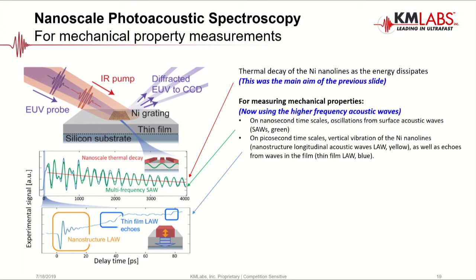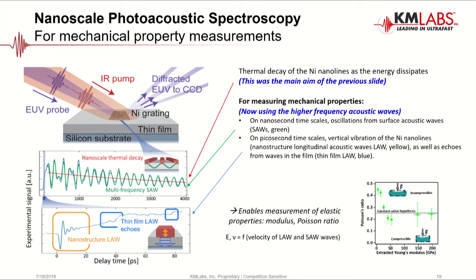And it turns out these are longitudinal acoustic waves that can be attributed to acoustic wave vibration basically bouncing down through the nickel grating, through the thin film, off the substrate and back up. And when we analyze the frequency of these oscillations, it can tell us about the mechanics going on within both the grating and the thin film. And coupling this to some modeling, the researchers found that they could extract things like the Young's modulus and the Poisson ratio of that film and plot the relationship between the two and actually see some interesting behavior depending on the composition of that film.